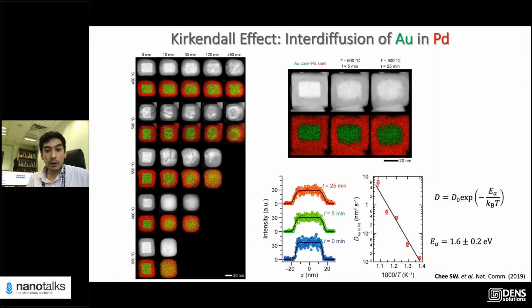At t equals 0, you have a very sharp edge profile, and as you heat for longer and longer, you see this profile becoming diffuse, and this is a standard double-sided error function from which you can extract the diffusion coefficient. The details are in Chee's paper, so I'm not going to go into this, but from this you can figure out the diffusion coefficient, because diffusion with temperature should show Arrhenius type behavior. The activation energy for diffusion is about 1.6 eV.